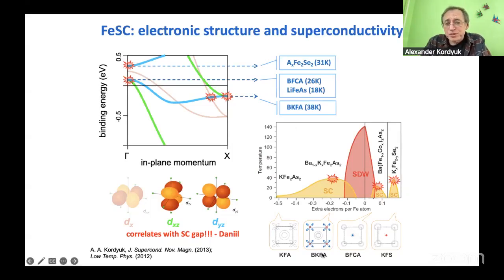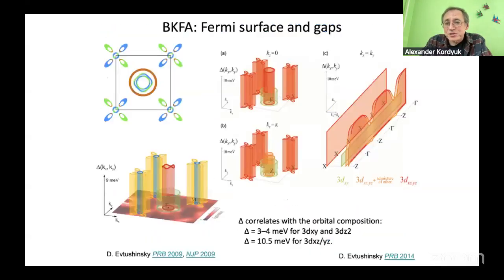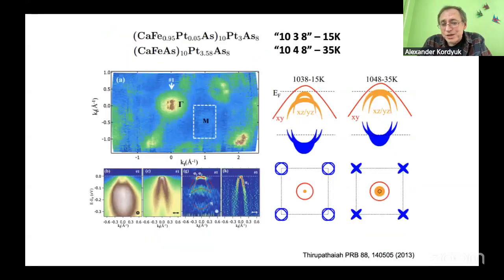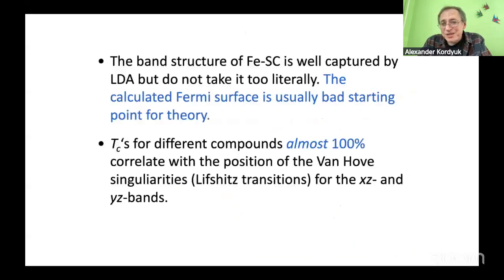From the point of view of Fermi surface, that means it is when the electronic structure is crossed by this Fermi level, and it is then a Fermi surface. And in 2 dimensions, we have a small Fermi surface. When it crosses here, it is this Fermi surface, crosses here, it is this Fermi surface, and you observe the maximal TC then. Still, there is no theory to explain it completely, but there are some ideas that these small Fermi surfaces work as an amplifier of superconductivity in larger Fermi surfaces.